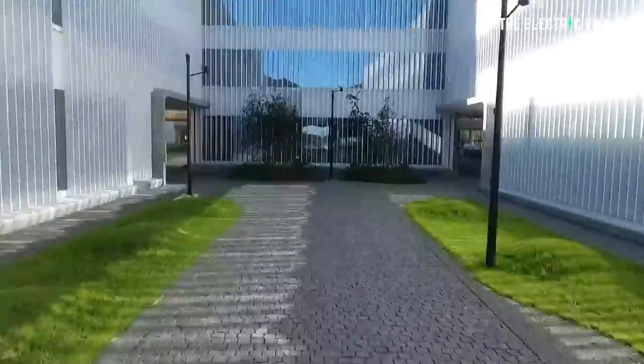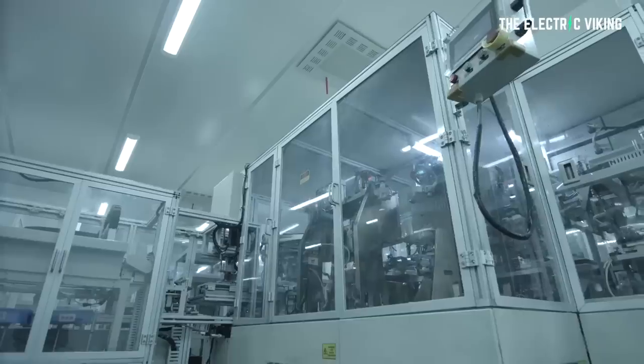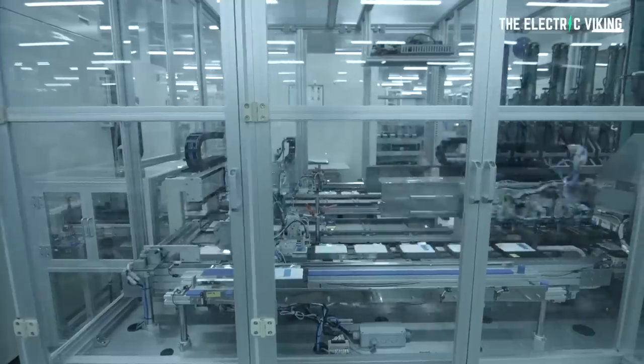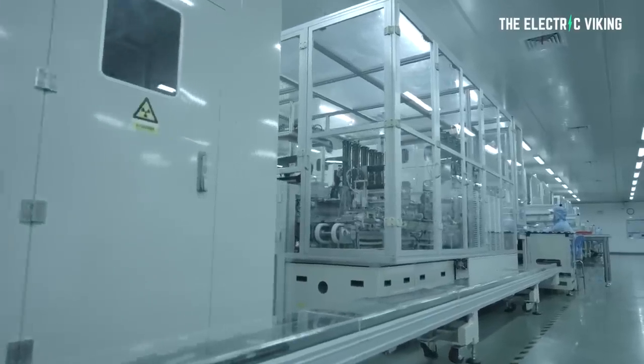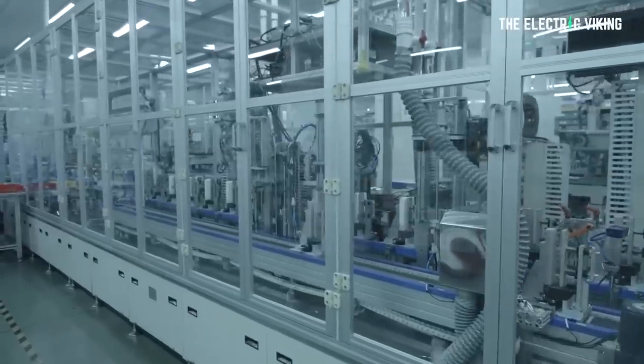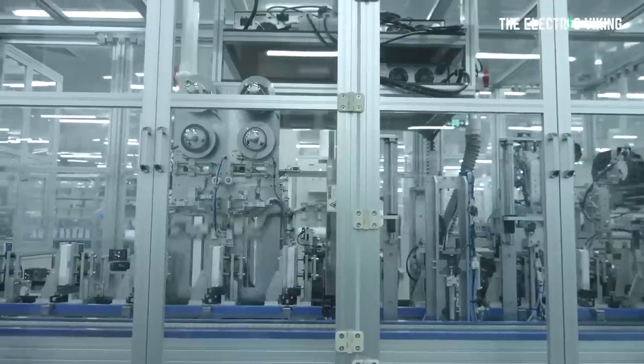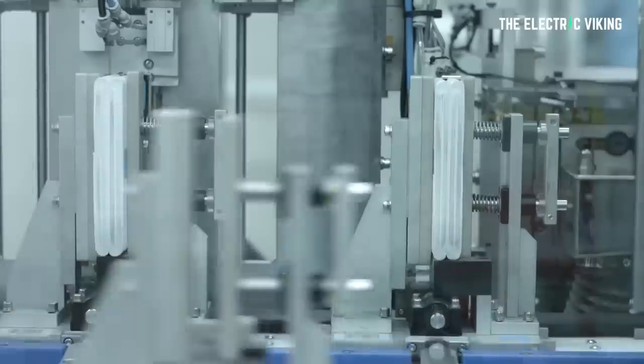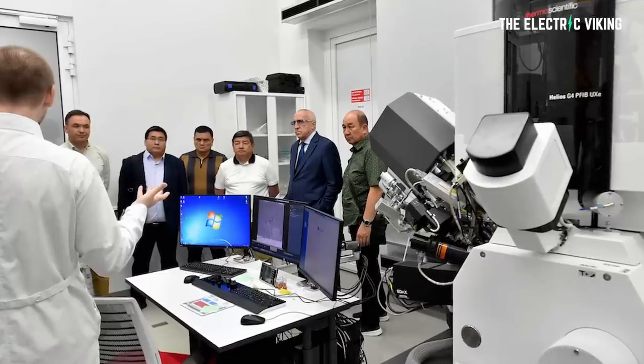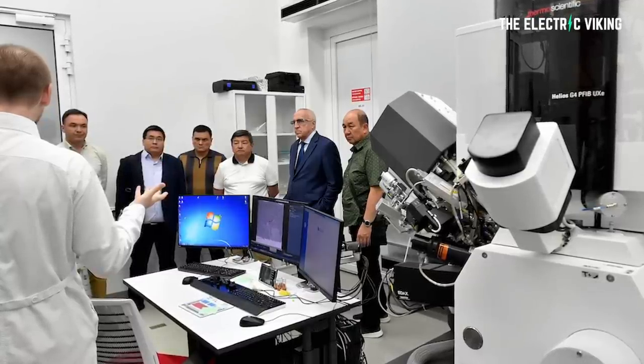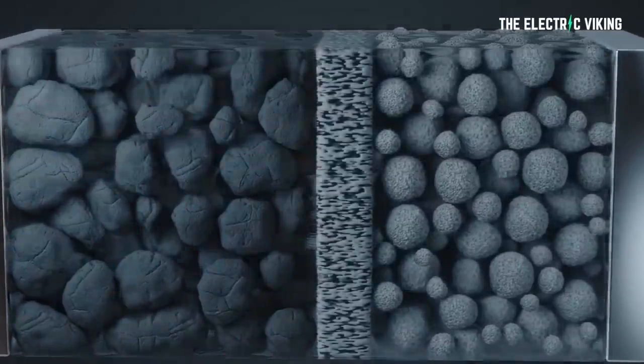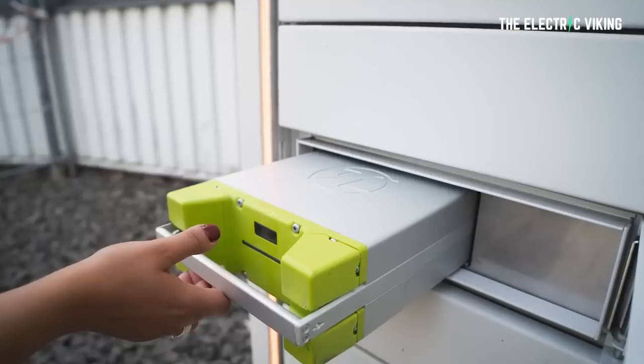To alter the layered oxide morphology, Skoltech researchers tweaked the synthesis procedure, which relies on the so-called flux method. Researchers say the new cathode material offers an increase in energy density by 25%. They hope that even more energy can be packed into the same volume through further experimentation with the particle size, combining smaller and larger spheres for even denser packing, which in turn would also increase the energy density and therefore the range of EVs. The team will also pursue layered transition metal oxides that would replace even more cobalt and manganese atoms with nickel, further enhancing energy storage capacity.